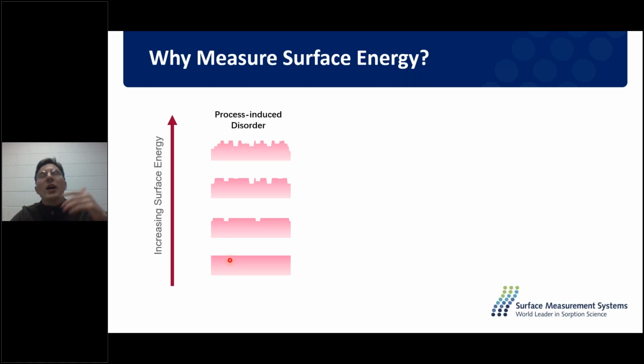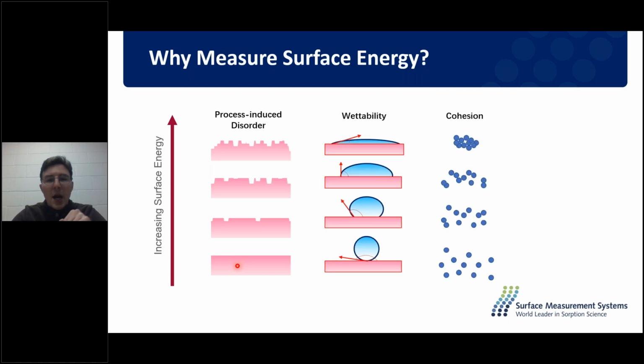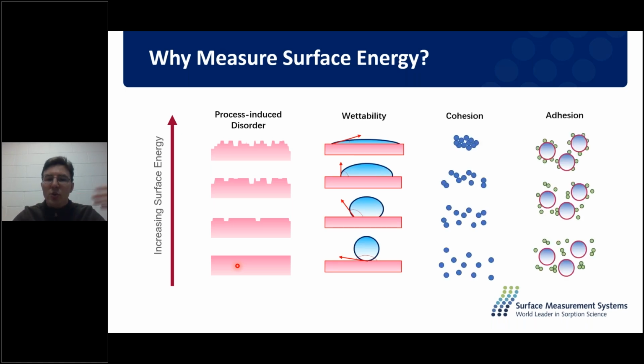At the bottom here, we have an ideal scenario. All of our surface atoms are equivalent. They are similarly satisfied. So we would say it's a more homogeneous surface and a lower surface energy surface. And we can predict this energy to a number of different properties. So a material that's going to have higher energy, we would expect it to have higher activity. So if you are a pharmaceutical, you have one batch of an API compared to another batch of an API, we would say that batch that has the higher energy would have the higher activity. So better bioavailability within the body.